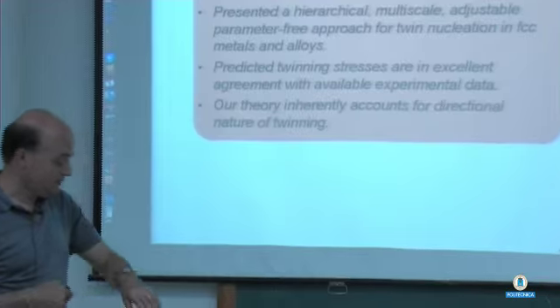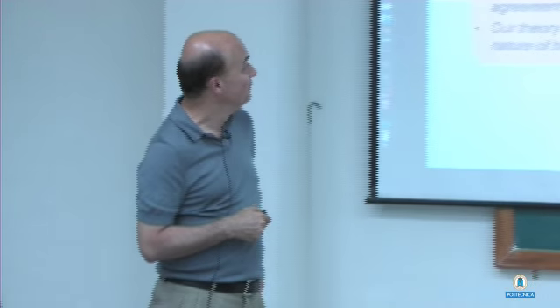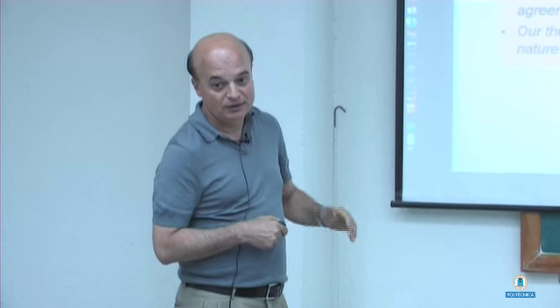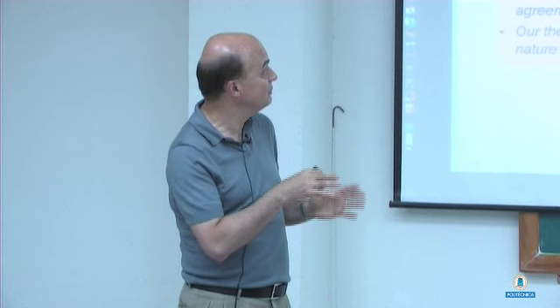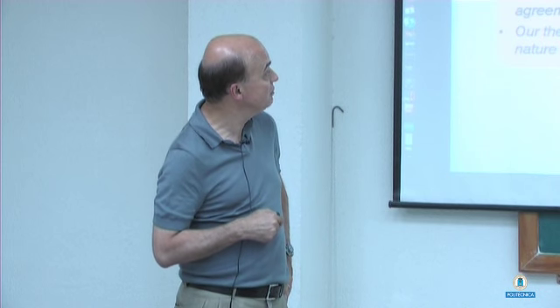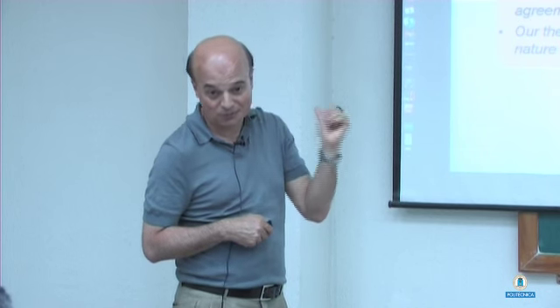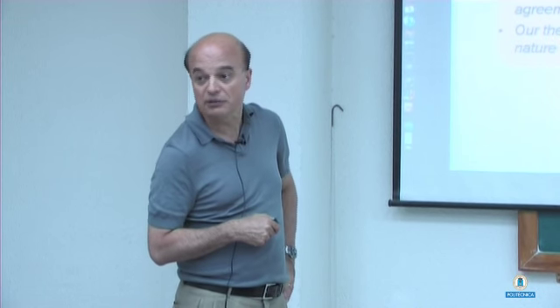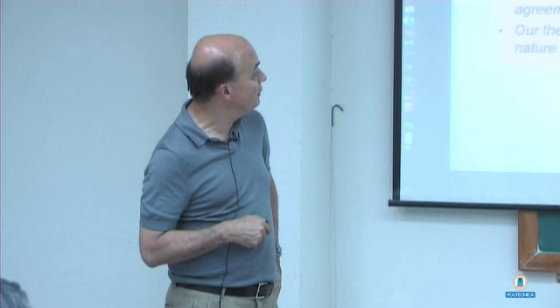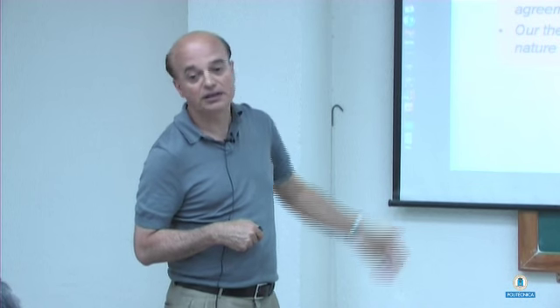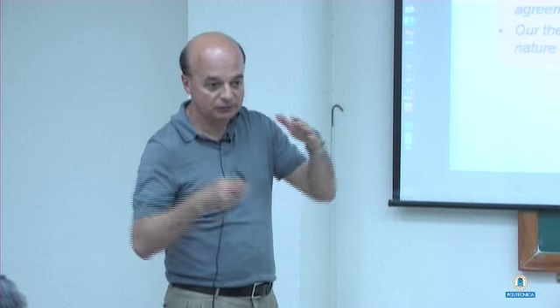I'm not quite done, but I'm going to do an intermediate summary. I presented a hierarchical, multi-scale, adjustable-parameter-free model, with no free parameters, for twin nucleation in FCC metals and alloys. I didn't do alloys yet. I'm going to do that next briefly. Predicted twinning stresses are in excellent agreement with available experimental data. It inherently accounts for the directional nature of twinning. That means it twins in one direction, not in the other.